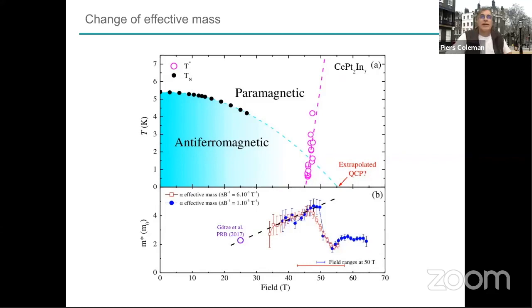To give some context, Alex, for example, in the neptunium 115 material, you see Curie behavior all the way down to TC, and also in the cerium cobalt indium 5, you see Curie behavior right down to TC. So it's curious to know what might be happening here. And also, how big, in terms of log 2, is the amount of entropy underneath the specific heat curve in the superconducting state? These are very large numbers in 115s, and so yeah, it's also large.